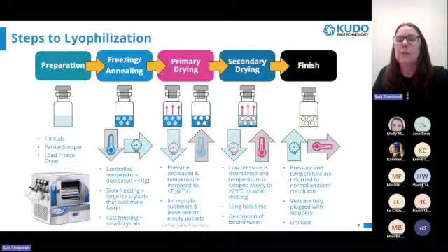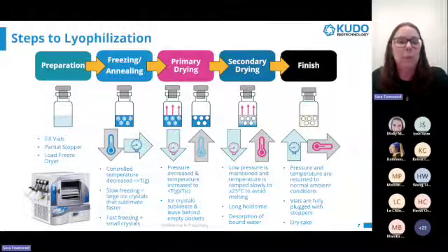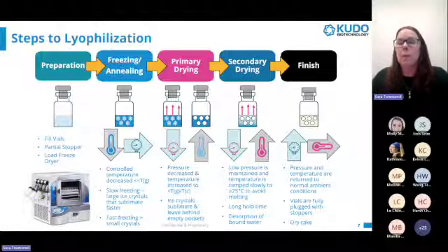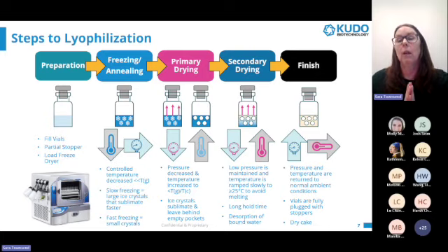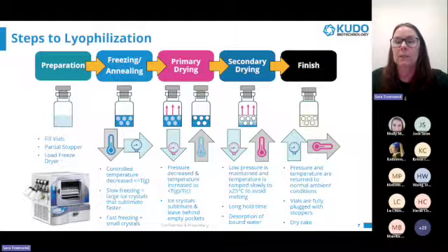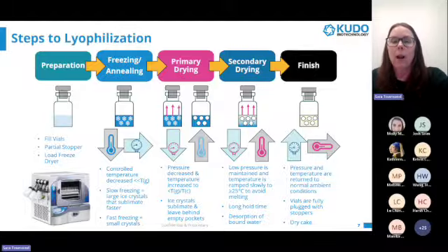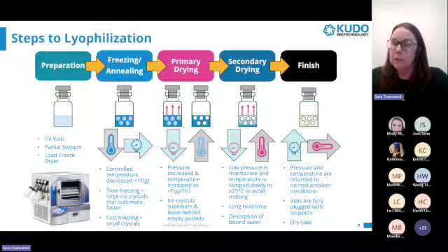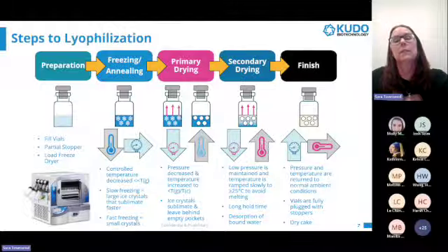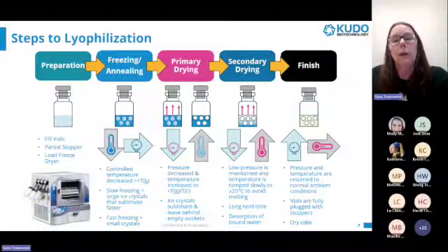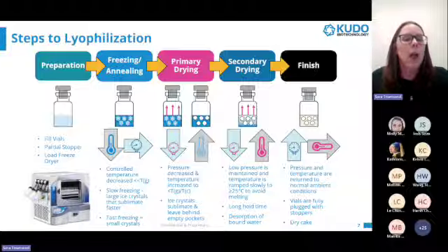The material is then frozen to a temperature that is well below the Tg temperature, and the free water will become ice crystals. This temperature ramp is controlled because slow freezing will cause large ice crystals that will sublimate faster, and fast freezing will give small crystals. The large ice crystals are generally preferred because not only will they shorten the primary drying step, they also won't raise the temperature of the product and cause meltback. However, for some drug products, large ice crystals can be damaging to the product. So it is essential to understand and learn about your particular product and which would be preferred.